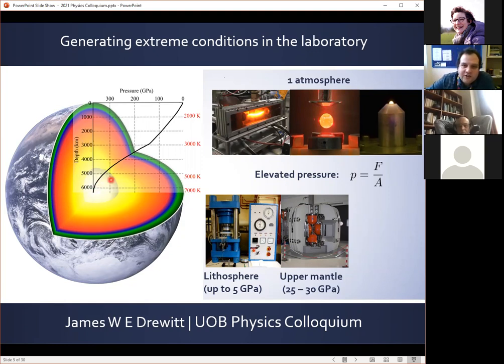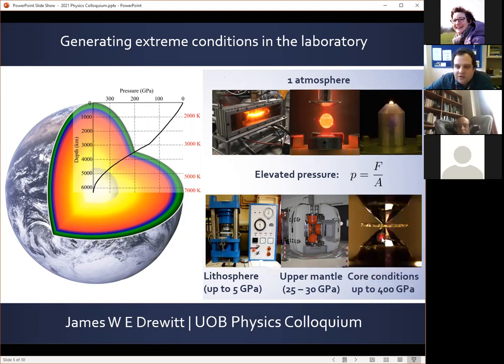So in order to generate these very extreme conditions, we have to use a different approach, and we tend to use the diamond anvil cell. And here we generate extreme pressures by minimizing the cross-sectional area of our sample that the force is applied over. And so using the diamond anvil cell technique, compressing a microscale sample between the tips of two diamonds, we can routinely generate conditions within the lower mantle of the Earth and planetary cores.